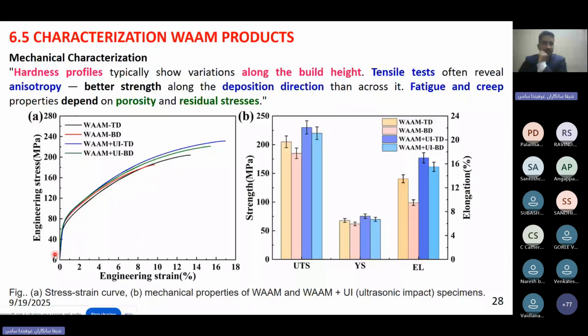Simply, once we build the component through the WAM technique, as I told you, most of the WAM product will exhibit anisotropic properties. It is not good actually, although for some applications it is fine. As much as possible, we have to minimize the anisotropic effect. In order to check the strength of the built product, what do we have to do? We have to cut the sample along the build direction and along the transverse direction, and then conduct the tensile test. Then we can see the behavior. For example, some researchers did this. This is the tensile stress-strain curve along the transverse deposition direction. This is the tensile stress-strain curve along the build direction. So the build direction is always weaker. Why? There is an interlayer.